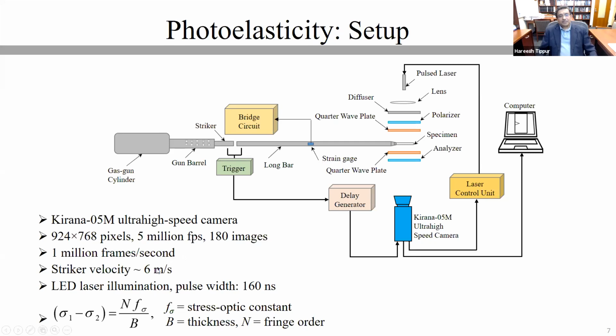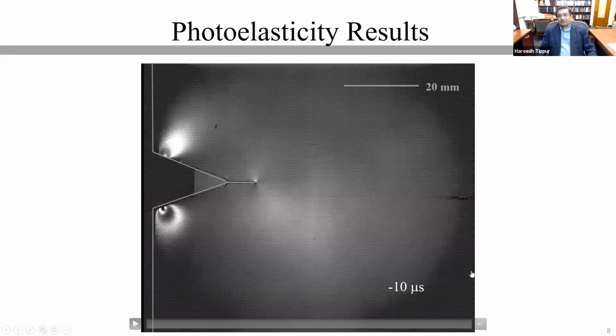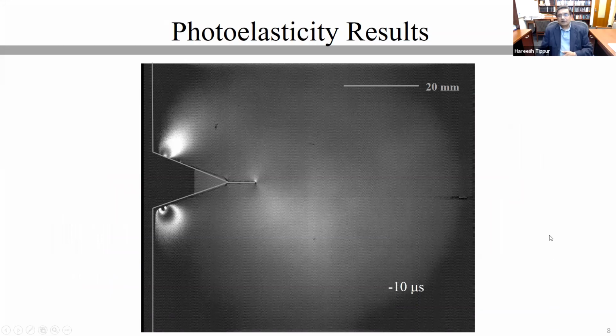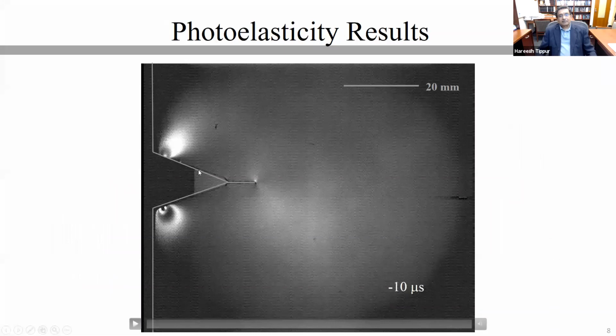The striker velocity that we used was a relatively low impact velocity of 6 meters per second. And as I noted before, the illumination was pulse illumination 160 nanoseconds long. And we are measuring the principal stress differences using photoelasticity in the form of fringes. So I'm going to play you a little animation to show the whole event and get an idea of what's going on. So here is the